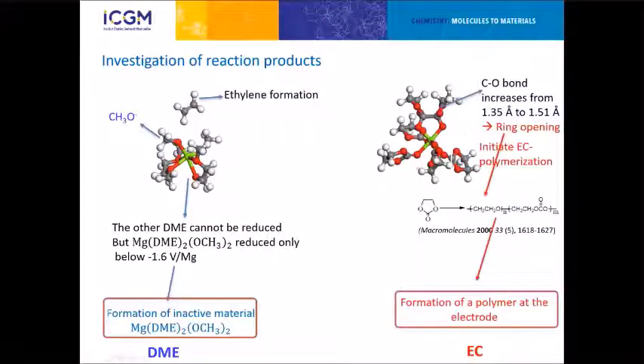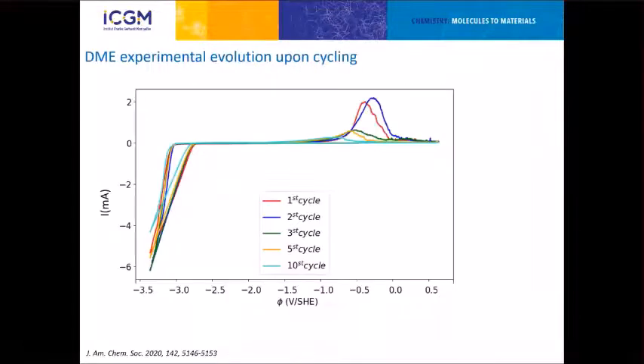In the second case, in the case of ethylene carbonate, we form the dimer, but what we see is a strong ring opening tendency. And when ethylene carbonate undergoes ring opening, it tends to form a polymer. So the problem with ethylene carbonate, which should be a better solvent, is that it is going to initiate a polymerization reaction at the electrode. That is not a very good idea because it's certainly going to passivate the electrodes.